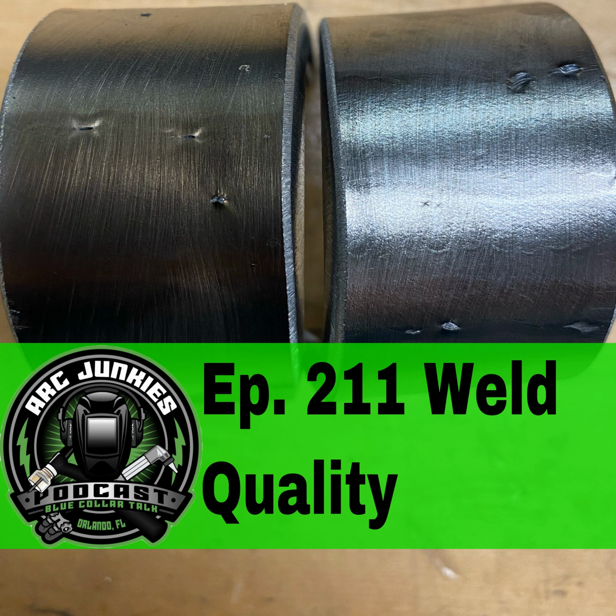The best way that I've found to do this is get yourself a decent set of dental picks from the auto parts store or off Amazon or wherever. You need a straight one and then an L-shaped or 90-degree dental pick. What that's going to allow you to do is dig in between your weld or at the toes of the weld, or anywhere where you have slag sticking that isn't coming out by a chip and hammer.